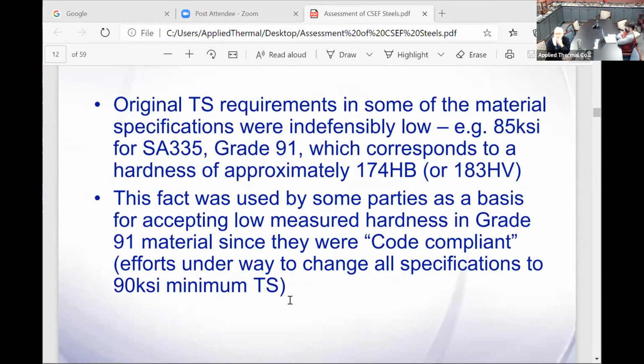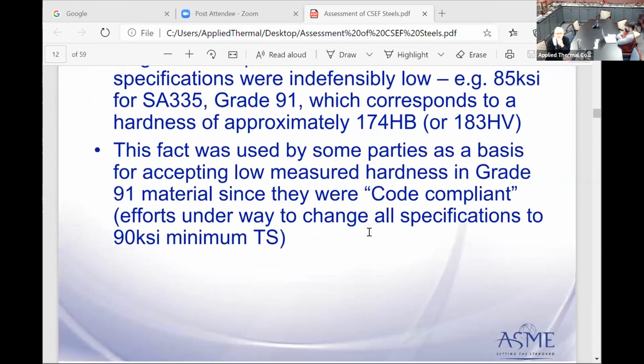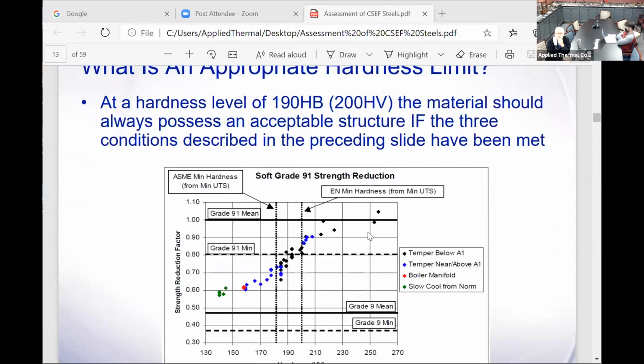A little bit more about hardness. It's very interesting. Apparently the original material specifications based on tensile strength and hardness show 85 ksi for 91, which is only a 174HB hardness. A lot of people think that number is way too low, and I'll go to this slide here. This is kind of interesting. At a hardness level of 190HB, material should always possess an acceptable structure if the 3 conditions described in the preceding slide have been met.